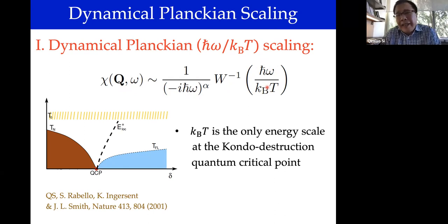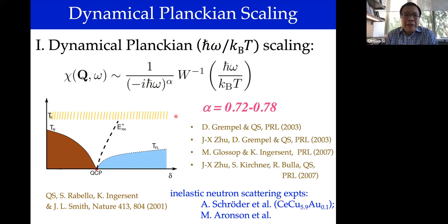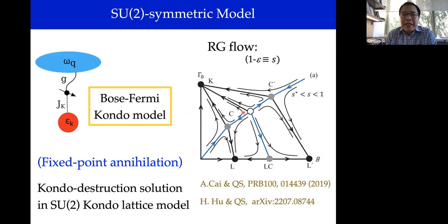So this type of scaling was the initial experimental contribution of Meigan Aronson and collaborators, and Almut Schröder and collaborators, and were in fact the initial motivation to consider quantum critical points that go beyond the order parameter fluctuations. And we spent the effort to calculate this exponent, especially in the Ising and isotropic case, and found the exponent to be indeed fractional, which was also the initial puzzle posed by the inelastic neutron scattering experiment, and the value is roughly in the range that was seen in the experiment in CeCu6 slightly doped with gold.